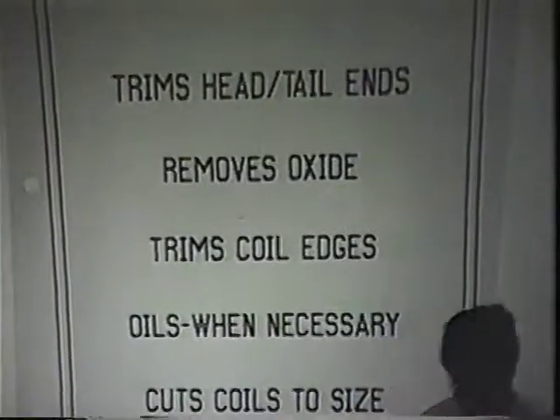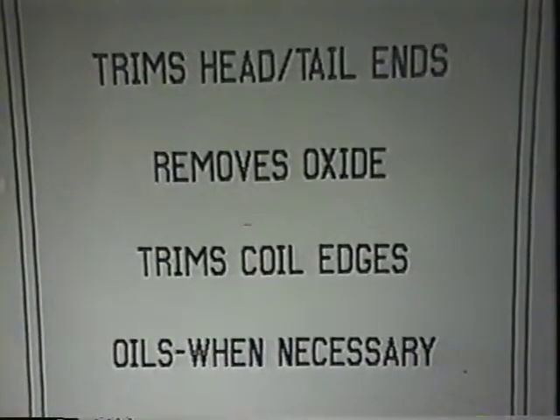But we're going to start off with the picklers because that's the first operation in the cold mill. The picklers, as you see here, are fed by the hot mill. A hot rolled product, the hot bands, are our raw material. As the schematic shows, we have two picklers at the cold mill. The primary purpose of the pickler is to remove oxide. Bottom line, it's to remove the oxide. If we didn't have to remove oxide, we wouldn't have to pickle.